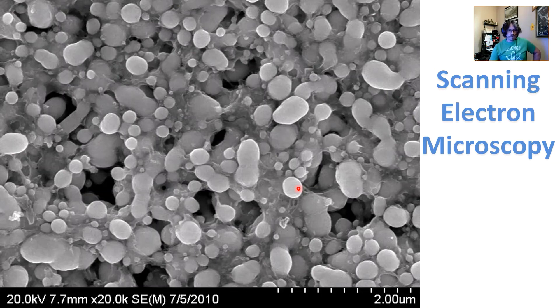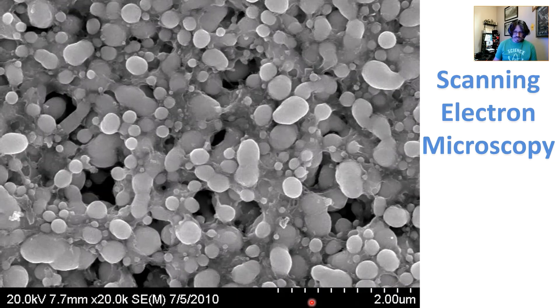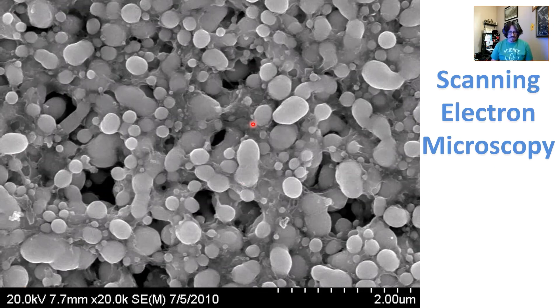Some interesting items to notice when you look at a micrograph: the magnification only applies to the original print magnification, so the micron marker is by far the most important piece of information — it allows you to turn qualitative information into quantitative. The accelerating voltage is generally listed on the micrograph; 20 kilovolts was used here on this field emission microscope. Working distance is the distance between the objective lens and your specimen — you typically want a shorter working distance for higher magnification imaging.